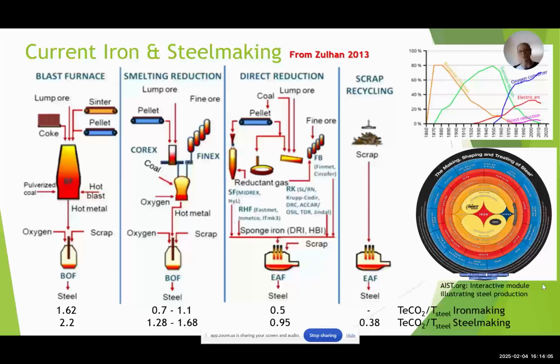Current steelmaking from Zulan 2013, it's a great chart. Blast furnace steelmaking to a BOF, smelt reduction to a BOF, also through a smelter, direct reduction in its various forms, be it shaft, rotary hearth, rotary kiln, or fine ores through the FinMet type process, to an EAF, and scrap 100% to an EAF. As you can see at the bottom here, the 2.2 tons of CO2 per ton of steelmaking drops down to 0.38 when we're looking at EAF steelmaking. And the right-hand globe here is the AIST's interactive module illustrating steel production, which you can access on their website.